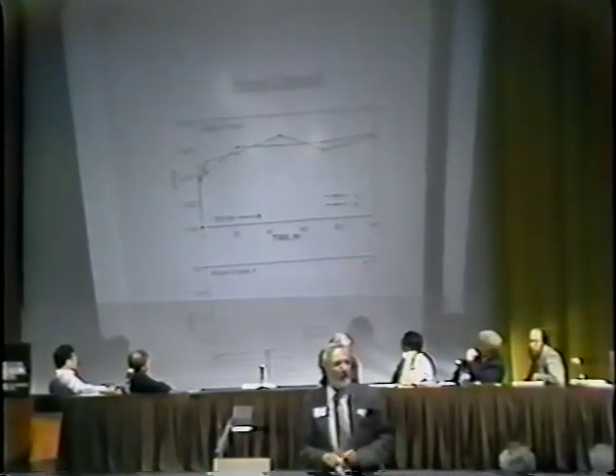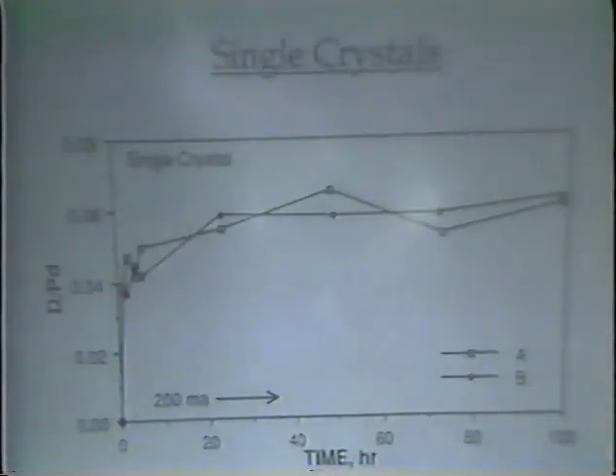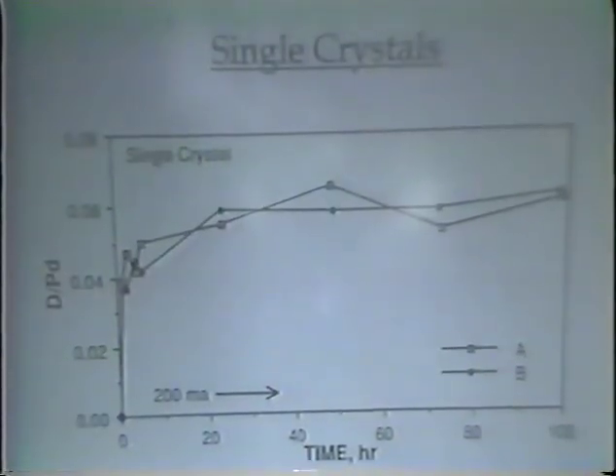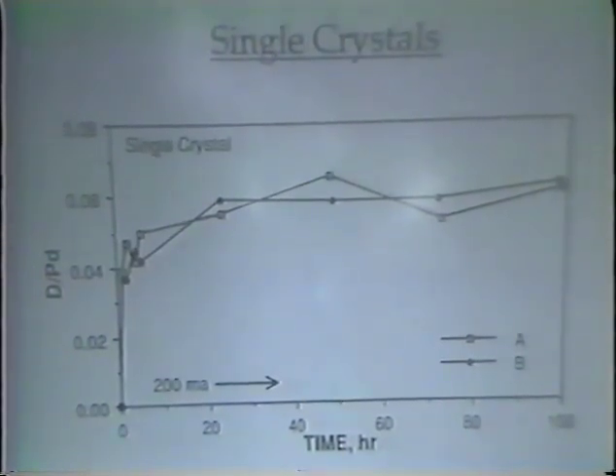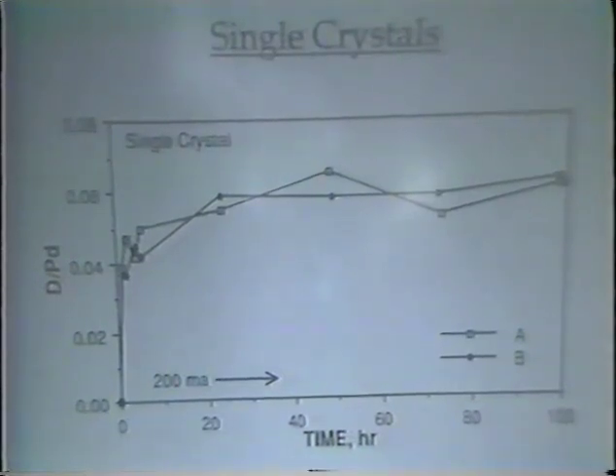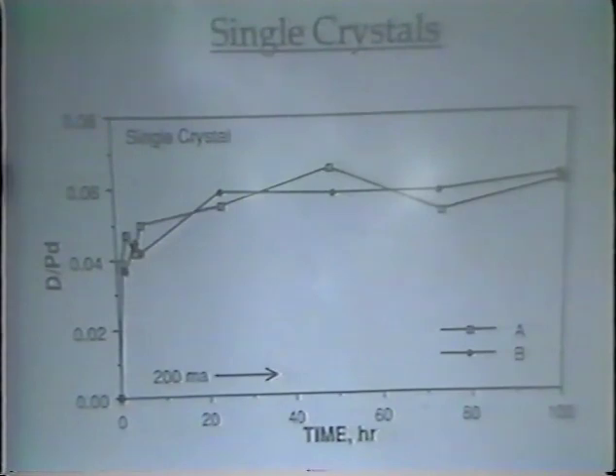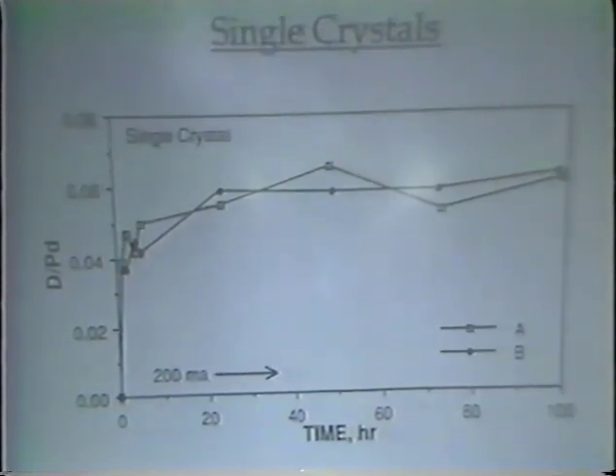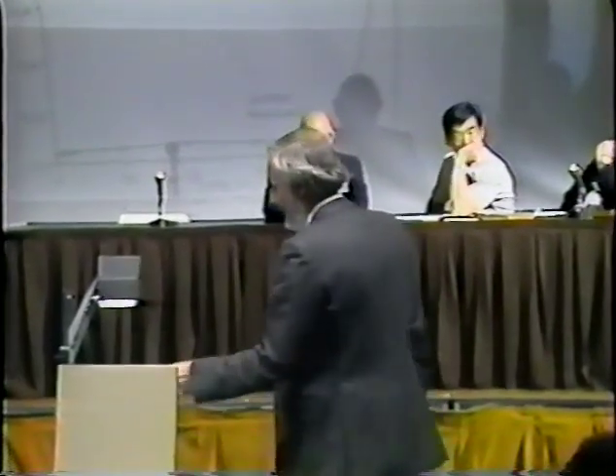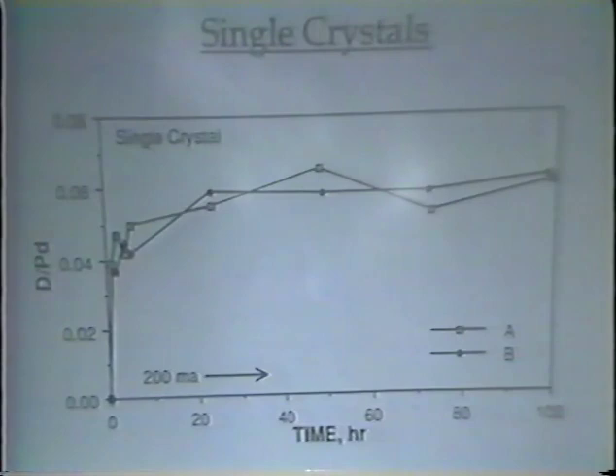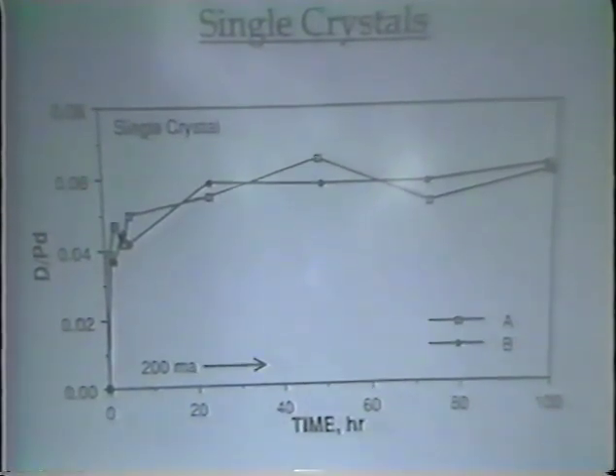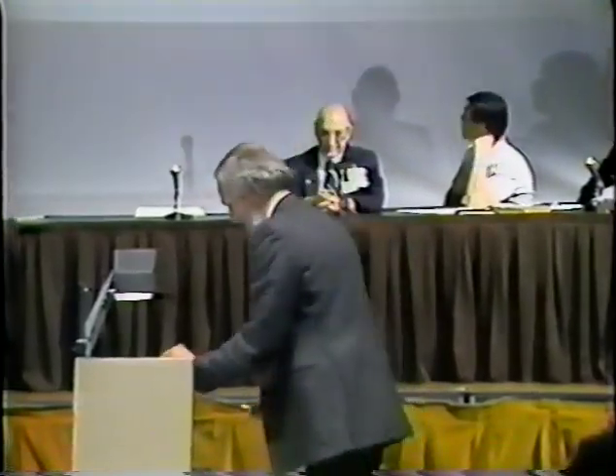Now, single crystals offer a unique opportunity to study the behavior in an environment that's a little less compromised by dislocations and uncertainties as to how this thing goes together. We had two single crystals, one that was grown with the 100 plane parallel to the axis and the other grown with the 111 plane parallel to the axis. They both behaved exactly the same for 100 hours, taking up very little deuterium, typical of an annealed sample, as they would be. And so in keeping with our current reversal, we did that on this sample and promptly discovered that it came up to almost 0.08. One reversal. The other one now has been reversed and it's coming up, but not as nicely.